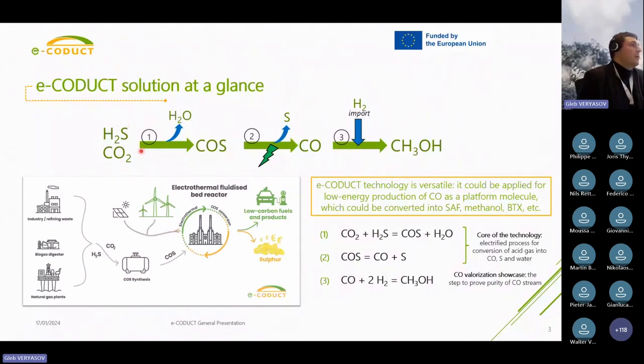We take the acid gas stream, we treat it with a special catalyst adsorbent, which will allow us to produce carbonyl sulfide selectively and to remove water. So water is a side stream for us, and it's also of value for certain regions where water is becoming a scarce resource. This is why we contribute to the water-energy nexus economy. Then this carbonyl sulfide is decomposed thermally to produce carbon monoxide and sulfur. And these two steps are the core of the e-CODUCT technology.